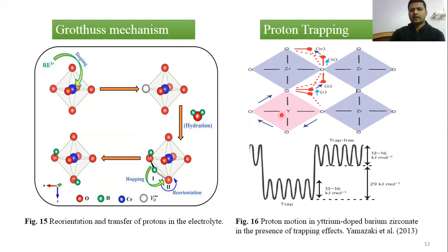Now, when we dope with rare earth, the B site becomes more electronegative, which leads to the trapping of protons. As we observed in this section, the arrow represents the trapping of protons at the rare earth site. So it requires some extra amount of energy to get itself mobilized to the other octahedra. So the proton path can be observed: within this yttrium octahedron, the proton gets trapped, while in the zirconium octahedron, the proton has sufficient energy to migrate. This was proposed by Yamazaki et al.